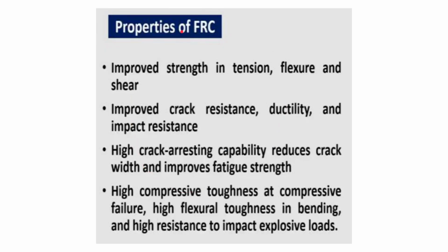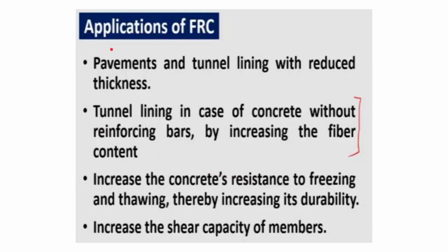Okay, so properties of FRC, therefore, we can say: improved strength in tension, flexure and shear, improved crack resistance, ductility and impact resistance, improved crack arresting capability, which reduces crack width and improves fatigue strength, high compressive toughness at compressive failure, high flexural toughness in bending, and high resistance to impact and explosive loads. Okay. Applications of FRC: they can be applied to pavements and tunnel lining with reduced thickness. Tunnel lining in case of concrete without reinforcing bars by increasing the fiber content.